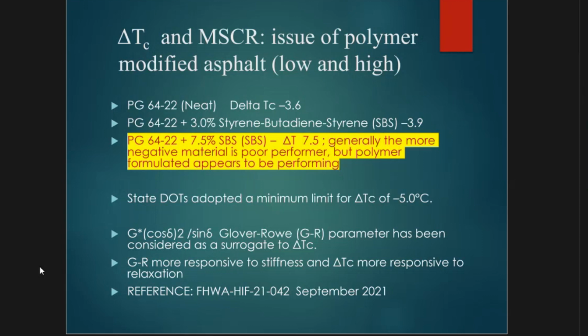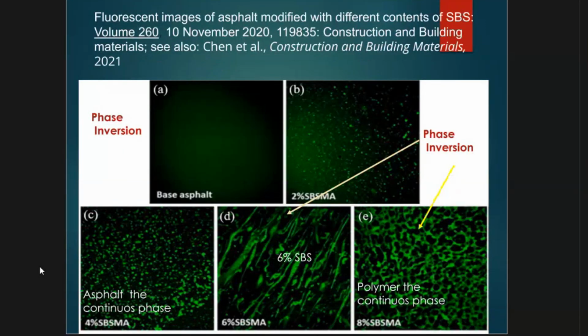All right. Let's talk about modification here. The base asphalt, you do fluorescence, and we have all these tools that we can look at. At 2%, if we do see polymer, it's a typical SBS polymer in asphalt, okay? And as you progress, the continuous phase is the asphalt, right? And as you go past 5-6% or higher, you get a phase inversion. The continuous phase is now polymer. Okay, it's not asphalt.